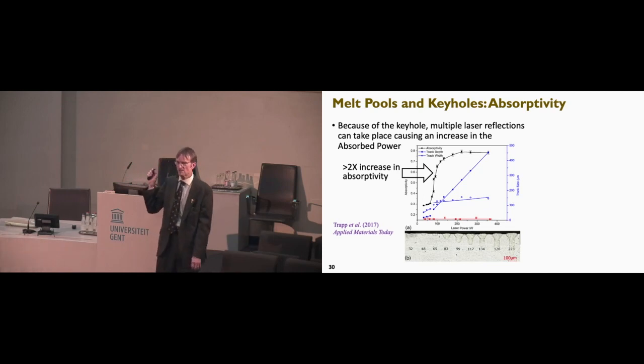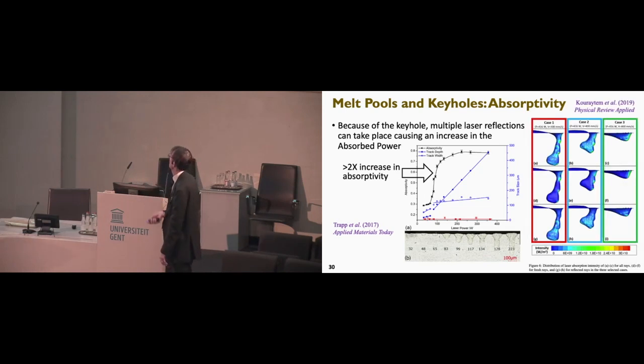And so my conclusion is that the laser powder bed machine manufacturers basically adopted keyholing as a way to get the efficiency up, to absorb more of the energy in a very practical sort of way. And yes, you can model this. These simulations are very expensive to do, but you can match what you see in the synchrotron quite well. And of course, several teams have been doing this, notably Lawrence Livermore.